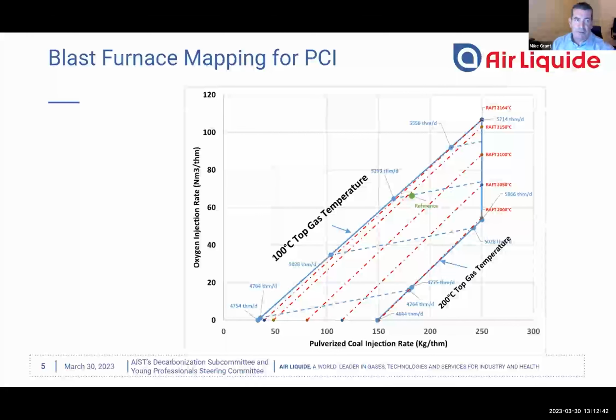Now, if we look at the operation of a blast furnace, we can characterize it using a blast furnace map. I like to call it a map. And what is it? It is a shape, and we look at fuel injection versus oxygen injection. We can see that we have this shape here, which actually defines the limitations of a particular blast furnace. They're not the same in every blast furnace, but this is an example, and you can see the reference point is shown here. This reference point is about 180 kilograms of pulverized coal injection per ton of hot metal, with an oxygen injection rate somewhere in the neighborhood of 65 or 70 cubic meters per ton of hot metal. And you can see these limitations are defined by the outline of this shape.